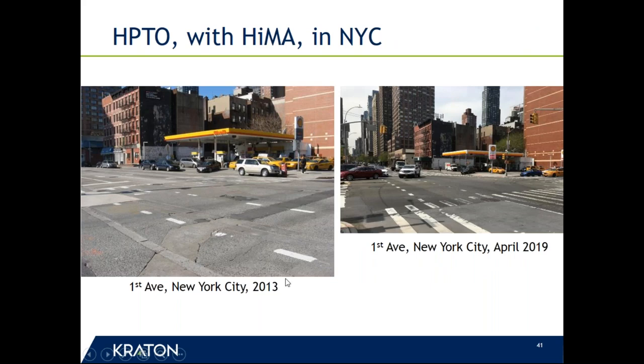This one on the left was taken in 2013. This is in Manhattan on First Avenue. And what they anticipate there is typically having to remove and replace the surface every 2 years. The original pavement here was a 17-inch thick jointed reinforced concrete pavement that the utility companies and traffic had ravaged over the years. What they did is they went in and did localized patching and repairs.